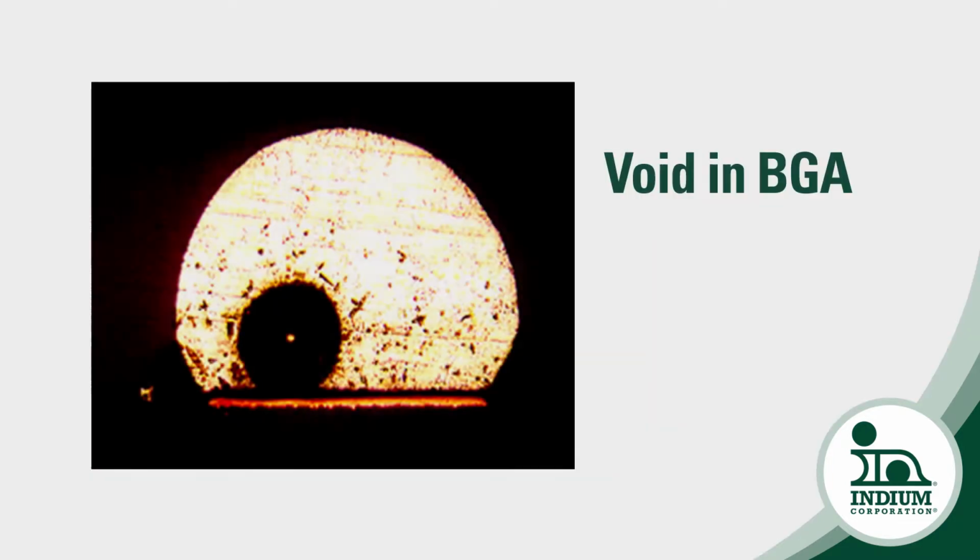Okay. How about our old nemesis, the via-in-pad? Via-in-pad, right? This happens a lot on BGAs. When the flux is outgassing, it gets caught up in that via and it creates a void. And of course, with the pitches of area arrays, BGAs, CSPs, flip chips getting finer and finer, down to 0.4 millimeter pitch, going down to 0.3 millimeter pitch, there's obviously less room for the designer to fan out in the dog bone pattern. So he's going to go with that old via-in-pad. Yep, exactly. You've got to watch out for that sometimes.